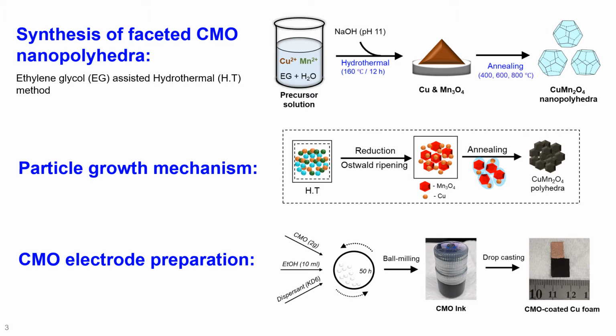And then the solution has been transferred to a Teflon lined autoclave to treat at 160 degrees Celsius for 12 hours. After naturally cooling down, the suspension has been taken from the hot air oven, and then this suspension was cleaned using DI water and ethanol a few times, and the final precipitate has been dried overnight. After that, the powder has been annealed at 3 different temperatures: 400, 600 and 800 degrees Celsius.